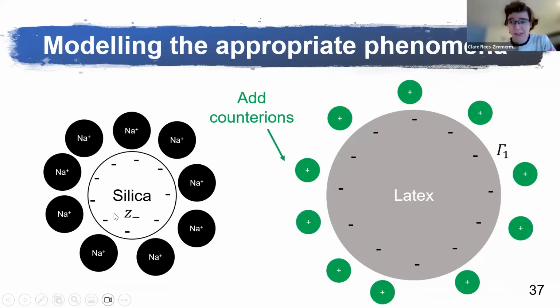In practice, it's not just the silica that would have counter ions. If our latex has a negative surface charge, it would have counter ions too. If there's only a small amount of latex compared to the silica, we could ignore this. But if we have comparable amounts of each, we would need to include this in our model too.